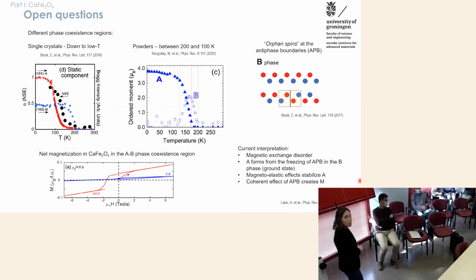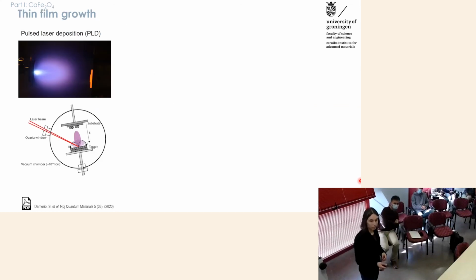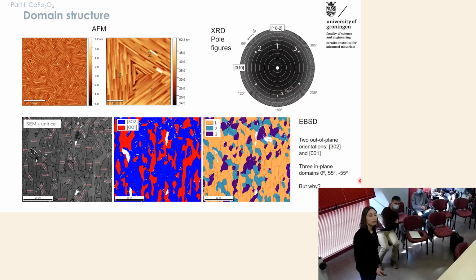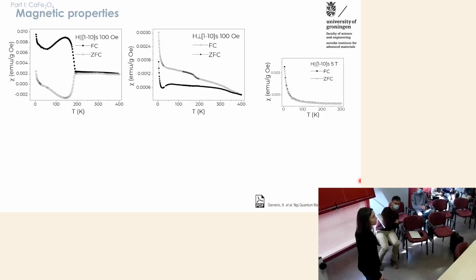In fact, if you show the slide of the magnetization along different directions, this one, you do see that between 400 kelvins and, let's say, 200 kelvins, over 200 degrees, you have a big hysteresis that you should not expect, I guess, in an antiferromagnetic material ordering at 120 or 180. Yes, it's a huge hysteresis.